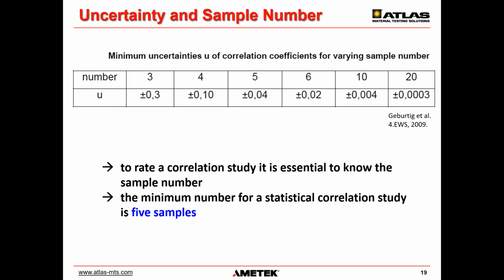What's important is the data uncertainty, and in statistics for Pearson, you can calculate the uncertainty based on the pairs you can vary. And with only 3 test specimens, which you compare in 2 test scenarios, the uncertainty is relatively high. So if you calculate, for example, a Pearson correlation coefficient of 0.7, the uncertainty is plus minus 0.3. So the variability is actually between 0.4 and 1.